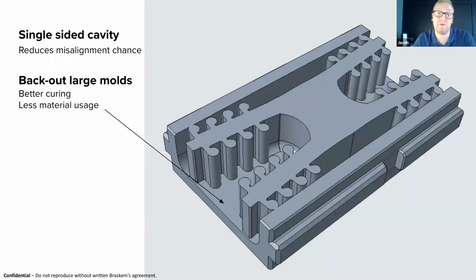We're only putting material where we need to resist those cavity pressures. This allows us to get better curing on the back, and we're also saving material usage that isn't making a big difference in the longevity of the mold. And then also, as Mark mentioned, alignment of the parting line. If you can keep that parting line very simple, you're going to have much better performance. So in our case, we were actually able to keep a single cavity and press up against a metal flat plated side of the mold. So it allowed for a great close off around the cavity, and I think it prolonged the longevity of our mold.